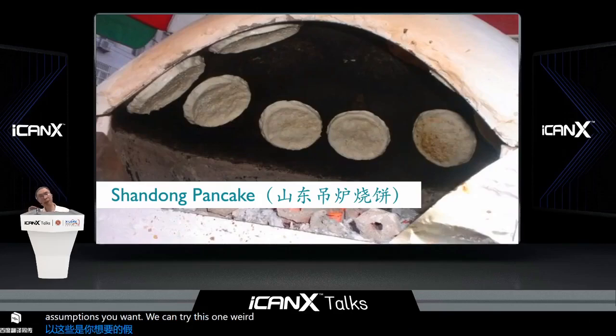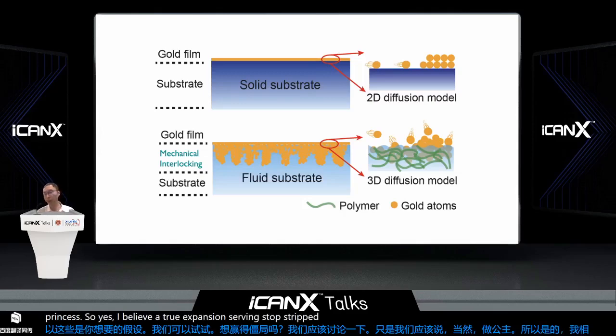And then this inspires us. We don't use this kind of solid state anymore. Can we just use a fluid state? But of course, it has to be processable. So I don't need to use a full fluid, but can use a so-called semi-cured substrate, for example, a semi-cured polymer. In PDMS, for example, which is a polymer, there are some monomers inside and also polymer associated. In this case, during the thermal deposition, the metal can diffuse inside.